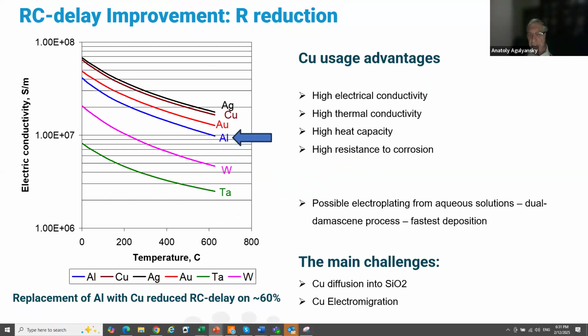About 25, 30 years ago, we switched from aluminum to copper. All metal lines were built from aluminum. And one day, people decided that we should switch to copper because copper is much more conductive. I show here electric conductivity versus temperature, in order not to show you just one point, these curves. And we win 60% due to replacement of aluminum with copper.